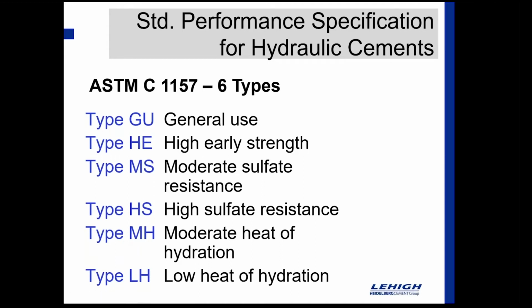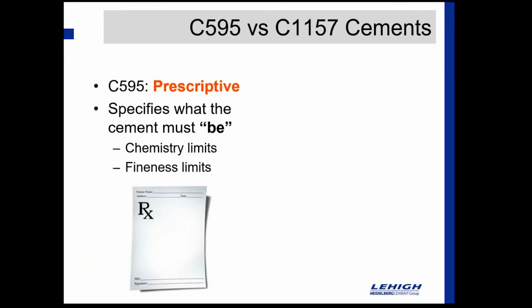And so we can kind of break it down like this, that when we look at C595 versus C1157 cements, C595 is prescriptive, so that specifies what the cement must be. In other words, there's going to be certain limits on chemistry or components of that chemistry that you have to maintain either over or under, and then there may be things like physical characteristics like the fineness limit that you've got to bear in mind as you're producing the cement.